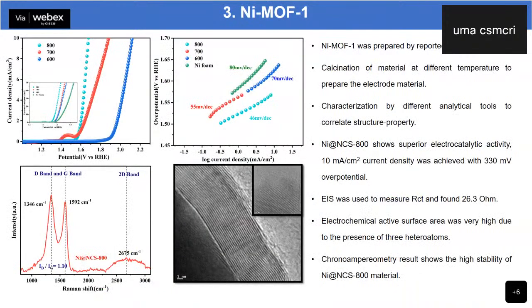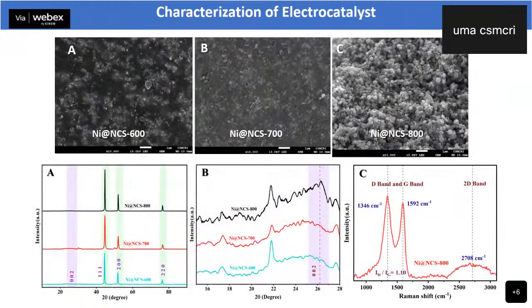Then in the third one, a nickel-based material was prepared. In this material, there are more heteroatoms: sulfur, nitrogen, and oxygen. Then the material was again prepared by the reported route, calcined at different calcination temperatures, and characterized by different analytical techniques. From the SEM image, you can clearly see the graphitization of the organic moiety with increasing temperature. Graphitization of carbon increases. When we compare nickel 600 and 700, we can clearly see that 600 has more organic moiety. Then when we compare the 700 and 800 materials, we can clearly see more graphitic material in nickel 800, and also the hierarchical structure of nickel nanoparticles. The metallic nature of the nickel nanoparticles was confirmed by XRD, and the graphitization of the carbon organic moiety was confirmed by Raman analysis.